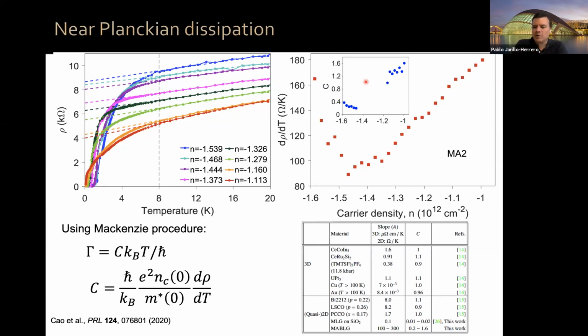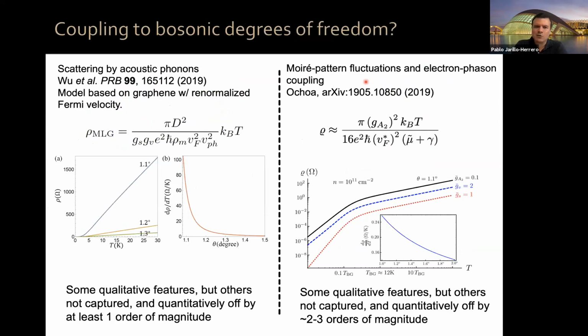Now, there are different possible explanations for this behavior. In particular, if your electrons are coupled to bosonic degrees of freedom, for example phonons, you could exhibit linear in temperature resistivity behavior. Two papers that I'm aware of discussed the possibility of linear in temperature resistivity by scattering by acoustic phonons, and also Moire pattern fluctuations and electron-phason coupling, which involve different types of phonons. These theoretical models capture some qualitative features, in particular linear in temperature resistivity at high temperatures, but as you can see at low temperatures, it's always quadratic.